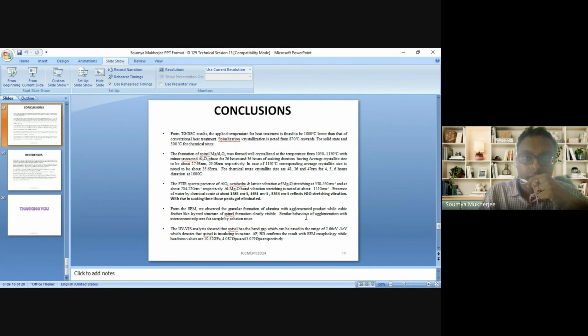UV-vis analysis was carried out and we are utilizing the Tauc correlation to measure the band gap. Apparent porosity and bulk density calculations have been carried out by making pellets, in conformation with the same morphology, in the case of solid state and in the case of the chemical route process. And we have measured the micro hardness, with corresponding values from 10 gigapascal to 5 gigapascal.